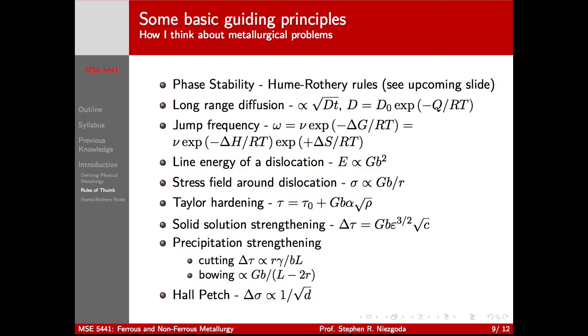Your shear modulus is going to be related to how far out that effect spreads. Poisson's ratio is in there too, but we can ignore it for now. Hardening: the yield strength is going to have a dependence on your dislocation density. That's work hardening.